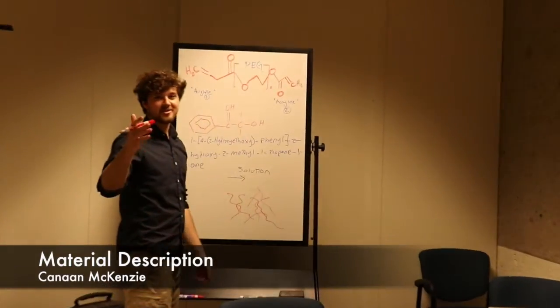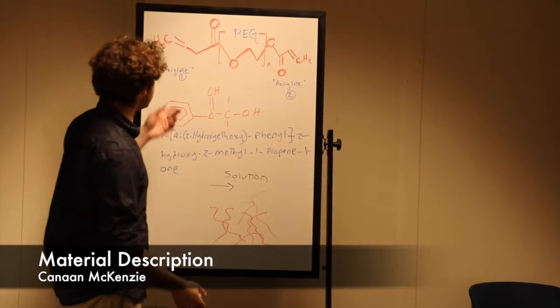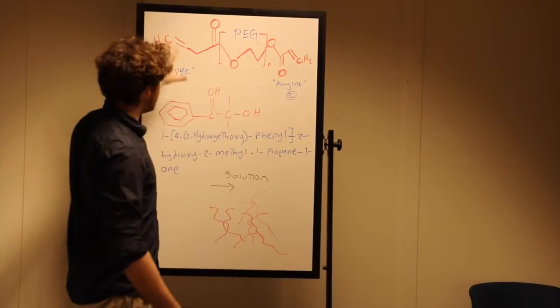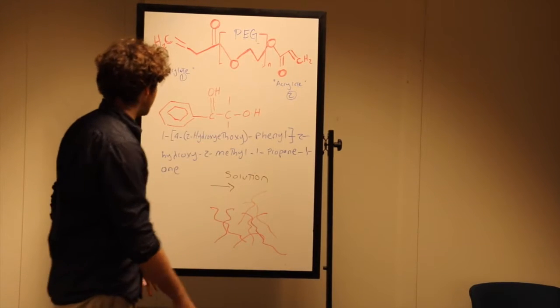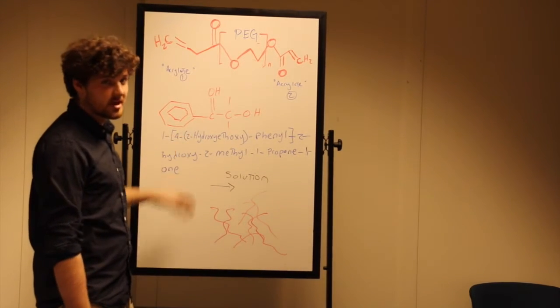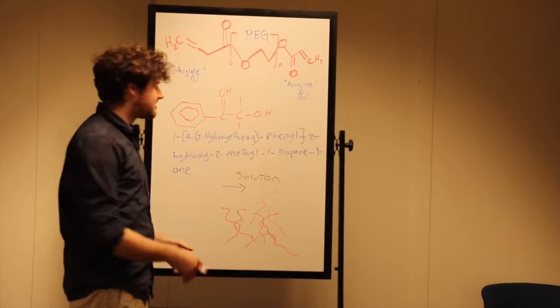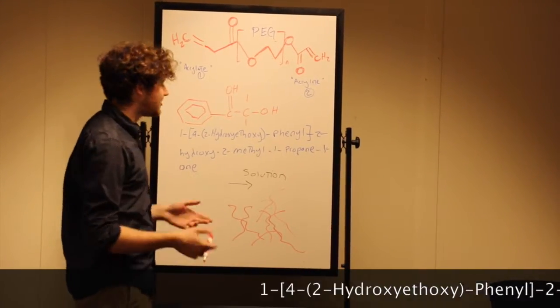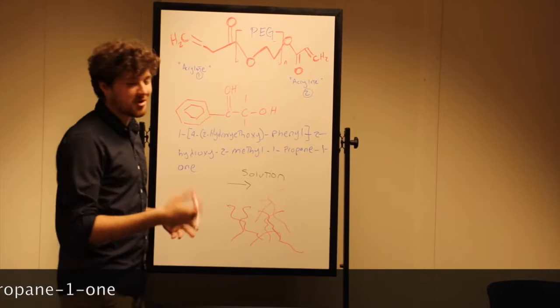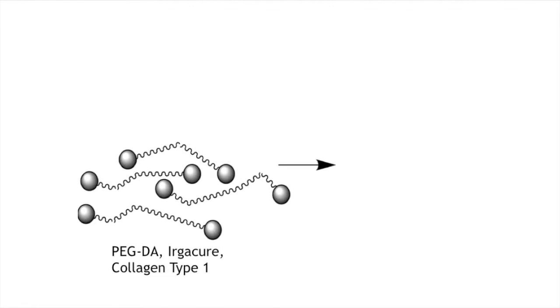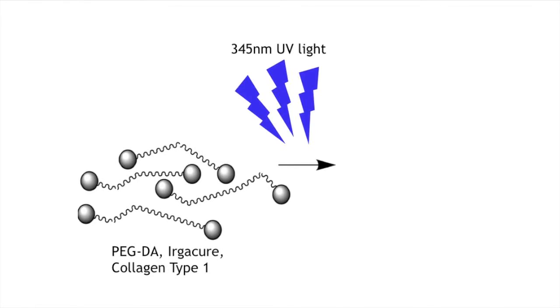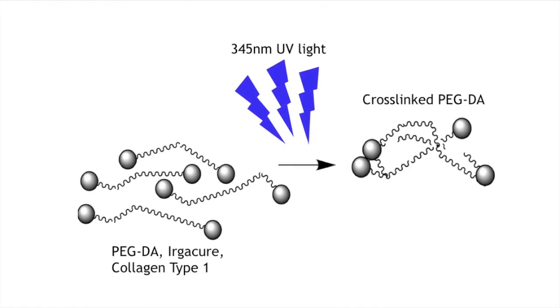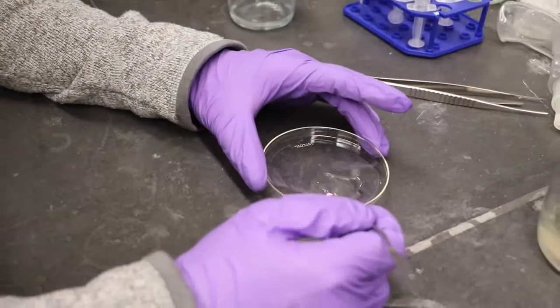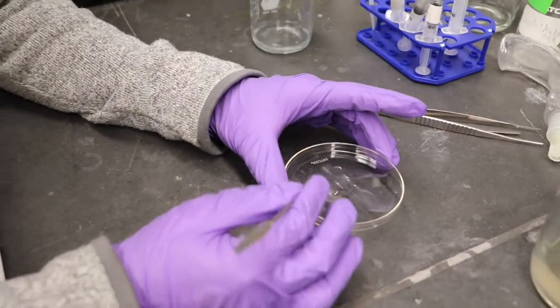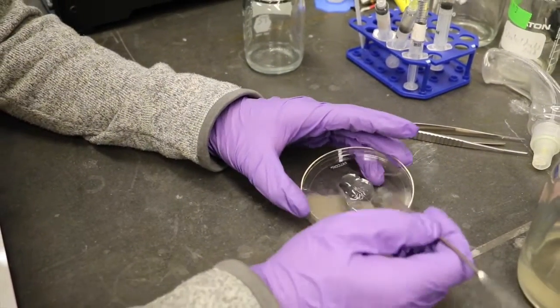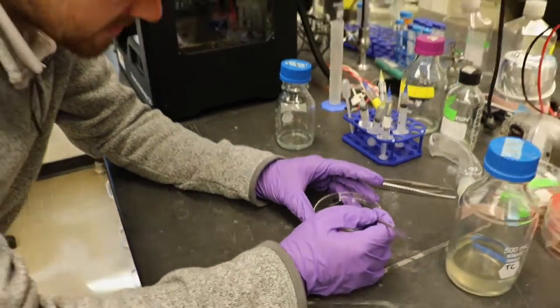So we took polyethylene glycol diacrylate, which, as you can see, is a polyethylene with two acrylate groups on the sides, and we mixed it with a photo initiator, commonly used for bioengineering standards. We mix those into solution in DI water, and with the addition of some UV light, it produces long chains. Those long chains interact to form a polymer lattice, which is effectively cured.